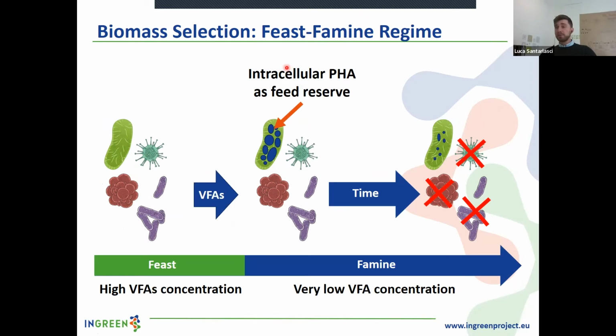The selection of the PHA-producing bacteria can be obtained by the so-called feast-famine cycles. During the feast phase, the feed is provided and all the microbial species start to consume the volatile fatty acids in the paper mill wastewater for cell growth and reproduction. When the VFA have been completely consumed, the famine phase starts and no more feed is provided to the microorganisms. In this way, for quite long famine periods, only species which can synthesize intracellular PHA as a feed reserve can survive, while the majority of other undesired species will die.